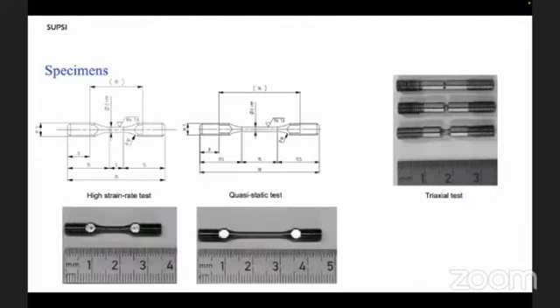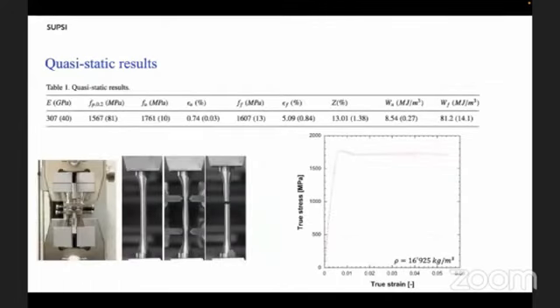Testing was conducted on smooth round specimens of 2 millimeter in diameter and 5 millimeter gauge length. Three notch configurations were used to evaluate the effects of different triaxiality conditions on stress and strain, keeping constant the net cross section of 2 millimeter in diameter. The quasi-static tests were carried out by means of an electromechanical universal machine, highlighting the elastoplastic and brittle behavior of